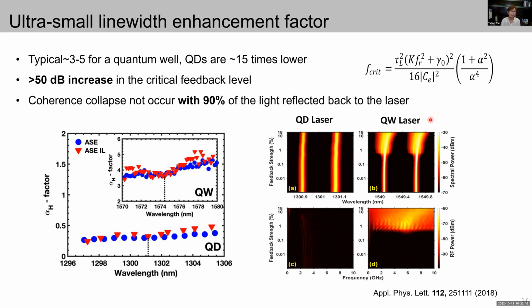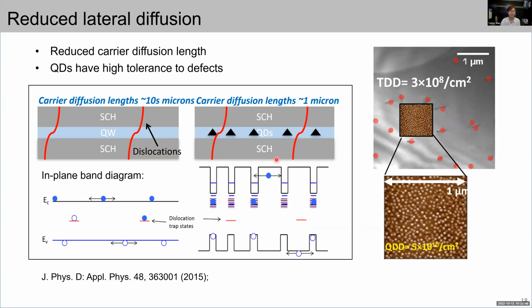But on the other hand, for a commercial quantum well device, even at a very low feedback level of minus 25 dB, you can see complete coherence collapse. This is very important to data communication systems, because with this reflection tolerant quantum dot active region, we don't have to incorporate external Faraday rotation-based optical isolators into the system to block the undesired reflections, which are bulky, expensive, greatly complicate the packaging, and can add additional insertion loss.